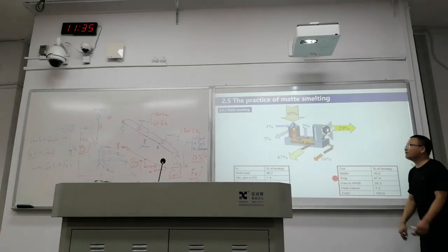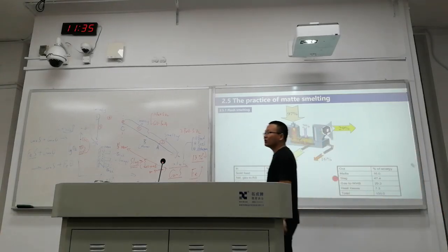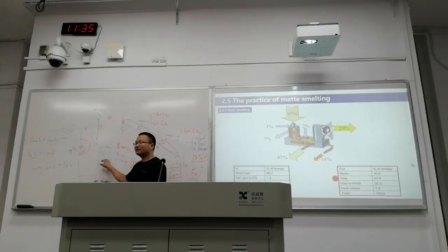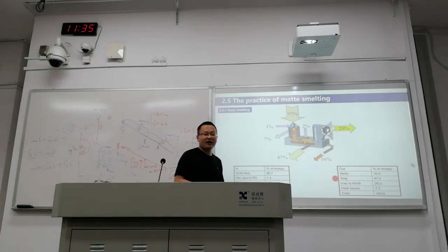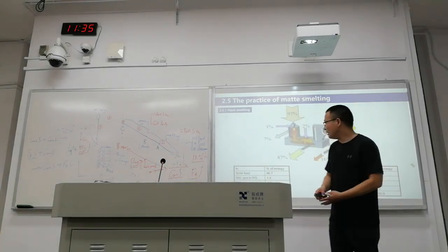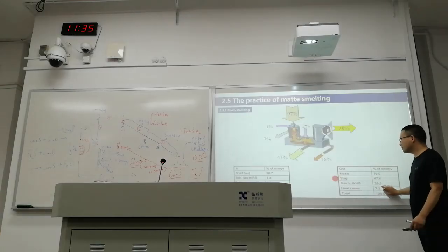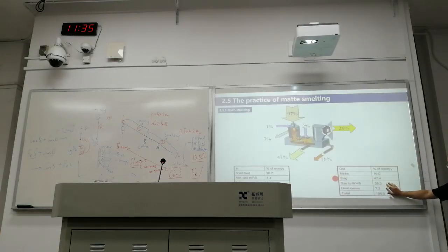For the heat loss, if we are using this water cooling jacket, cooling element, they are taking away some energy. And this part is for the purpose of protecting our furnace, right? So if we are having some heat loss, and we have these linings, the slag linings, it will help us in protecting our furnace. And the only other one is about the gas phase. If we are using less nitrogen, the gas will take less energy away, right? So the oxygen enrichment is a critical part.